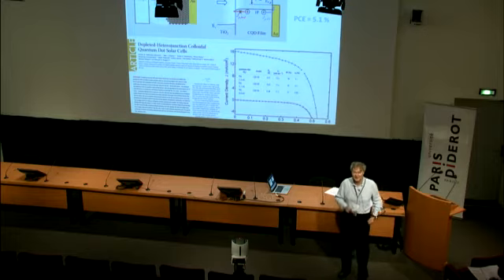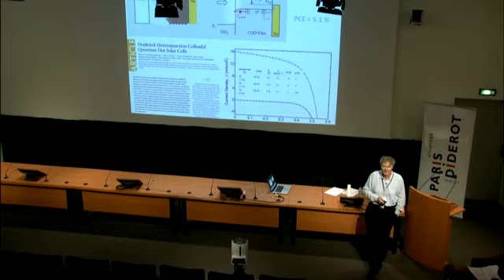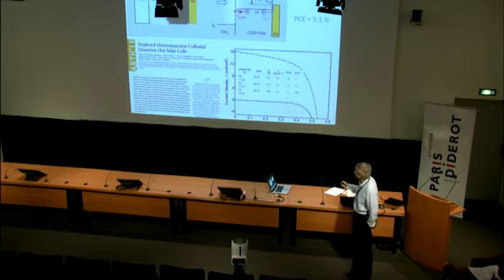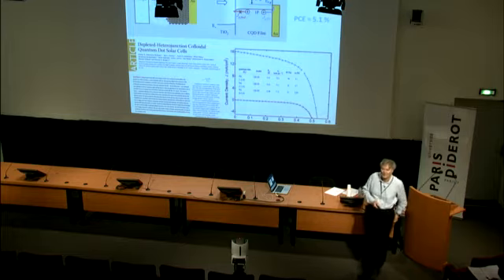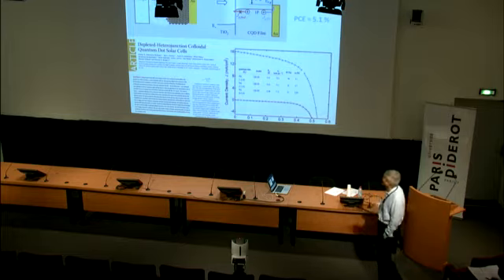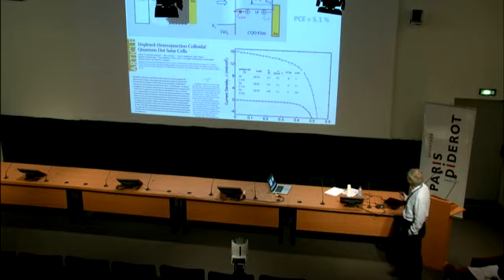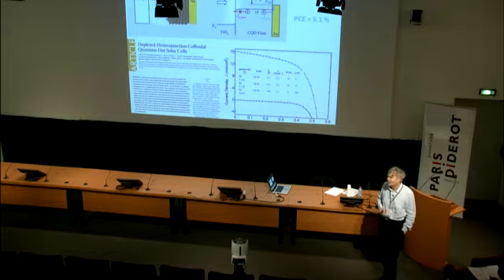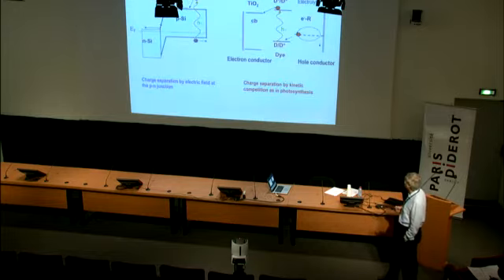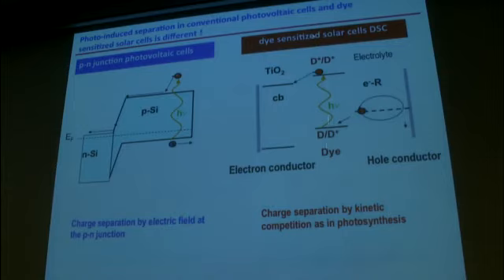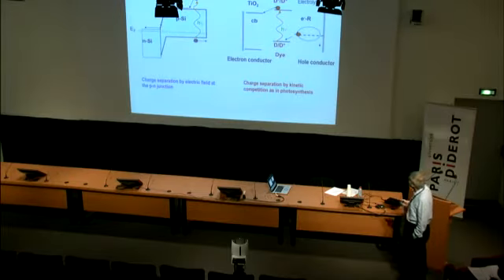Here's a system that works because the carrier lifetimes are long in lead sulfide. Carriers are coupling very well through the particles because of the very low effective electron mass and hole mass. So here's an exception. It doesn't work that well, but 5% power conversion efficiency has been achieved, certainly promising to move along this path. But as a rule, we have that separation. We have a dye or a nanoparticle, a quantum dot absorbing light, injecting electrons and injecting a hole in the electrolyte. So that's different from the charge separation in p-n junctions.